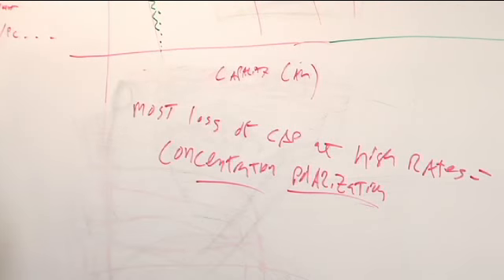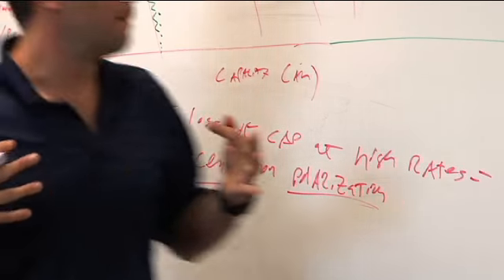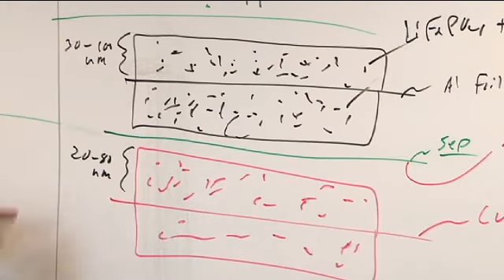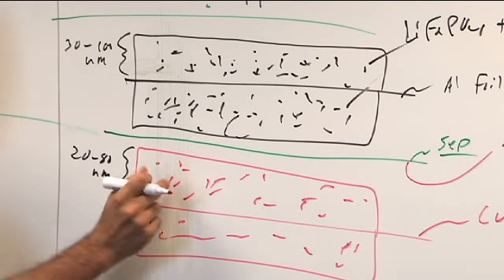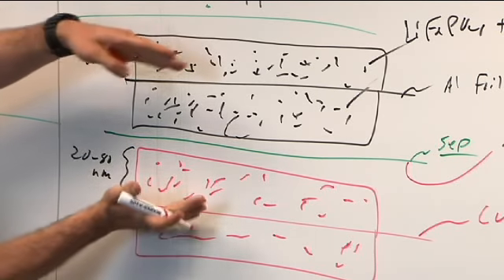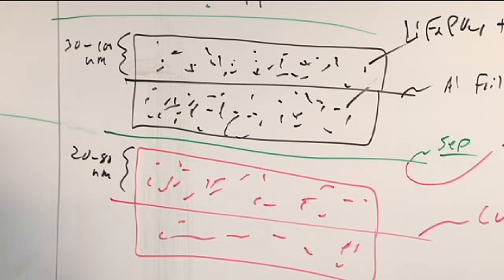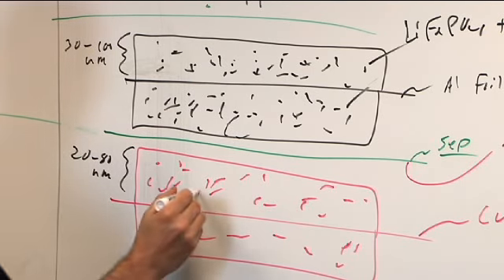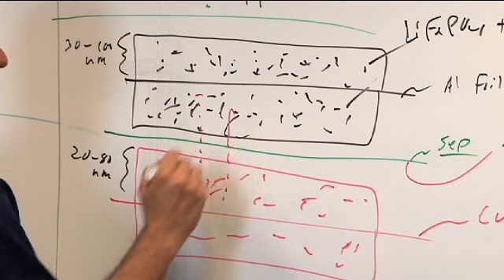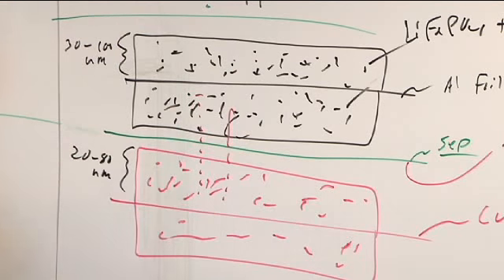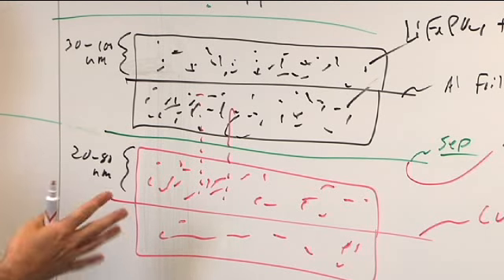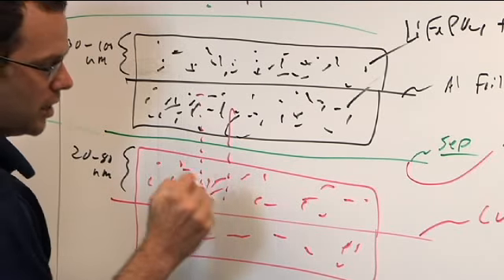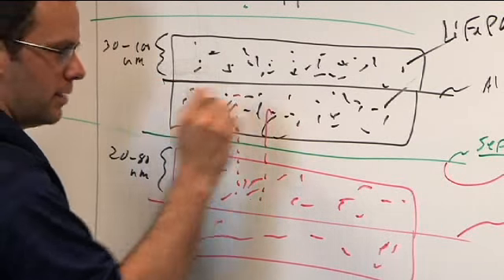All right, what is concentration polarization? Imagine now, really slowly, I'll stand so you can see it. Imagine I've got a fully charged battery, all my lithium is in my anode, and I'm just going to concentrate on this unit cell right here. All my lithium is here, and with a really slow discharge, I let my lithiums easily diffuse through here, and they go through no problem, okay? Now, imagine instead I almost short the cell, and I demand a huge amount of current. I allow a 20C rate through here. What happens is that we essentially overstuff lithium locally. It builds up so fast.